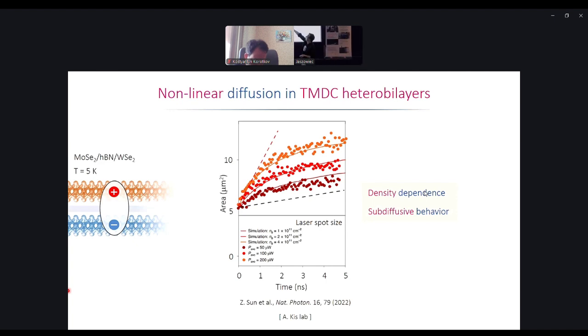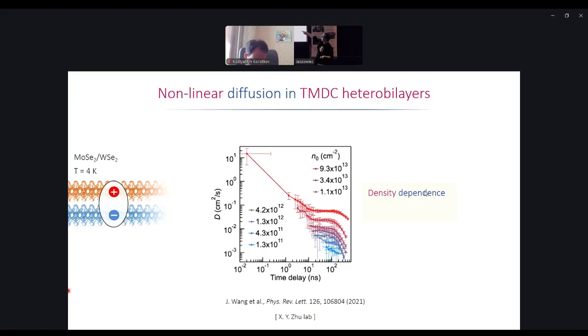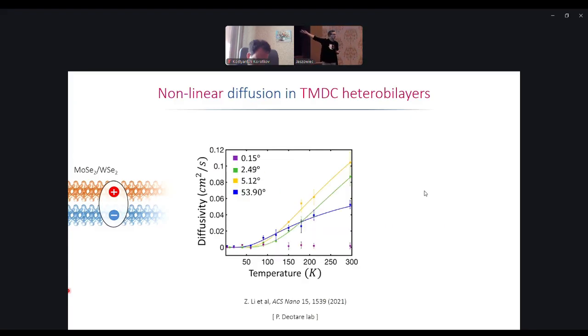Here, from bottom to top, the density increases, the diffusion becomes more and more subdiffusive, much faster and faster in the beginning, and then towards the later times, you get back to linear diffusivity. This is another way to look at it. This plot shows the extracted diffusivity for different densities. It's a little bit complicated, but in the end, what you also see here, the higher the density, the faster the excitons, and then in the linear regime, they are quite slow. And in this linear regime, you also see this temperature dependence, which means what? Semi-classics, hopping.